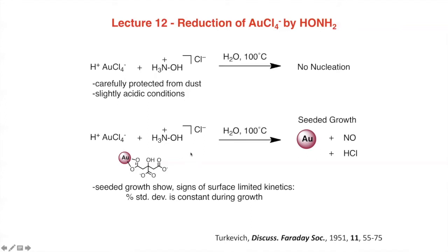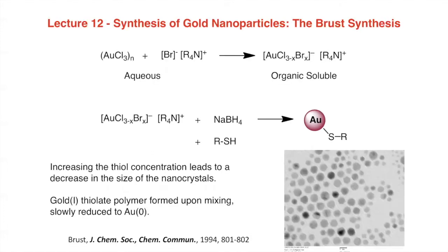And so when the reductant is selective in this way, when it's not powerful enough to make gold zero on its own, you'll get preferential reduction on the gold nanoparticle and autocatalytic growth. I haven't seen an example where somebody's shown an induction delay in the formation of gold and interpreted it to mean autocatalysis, but this is a clear signature of that kind of thing.